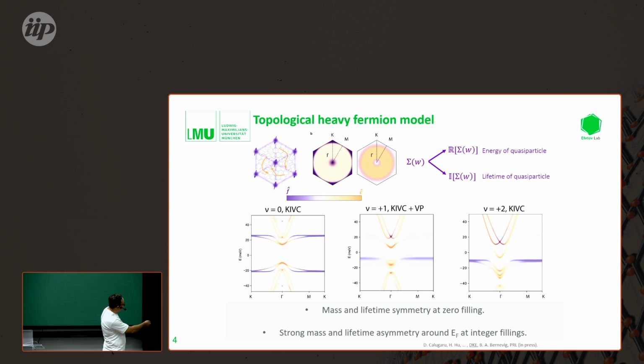So for example, for filling factor 1 or filling factor 2 states, on the electron side, you first dope into the dispersive bands, but on the hole side, you actually first start hitting the heavy fermion bands. And so we basically wanted to test some of these predictions, really the asymmetry between electron and hole excitations. And in normal transport measurements, we are insensitive to this. We cannot really see a big difference between electron or hole transport. The only thing that we saw in transport measurements is that we saw Shubnikov-de Haas oscillations when we were on the electron side, but we didn't see Shubnikov-de Haas oscillations originating from the hole side.